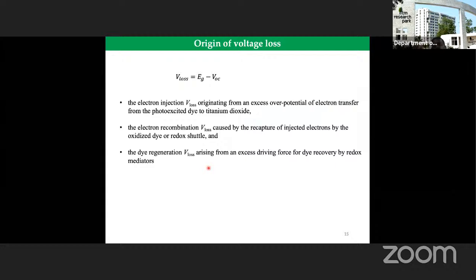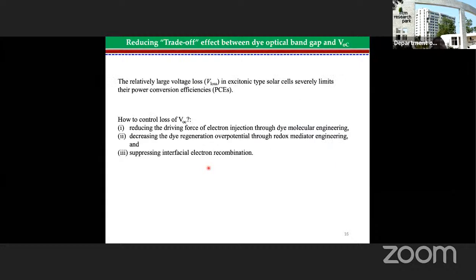So we need to control these 3, right? So how do you control this voltage loss? Reduce the driving force, that means a gap for electron injection, through dye molecular engineering. That's the only way. Decrease the dye regeneration over potential through redox mediator engineering, that means electrolyte has to be redone such that the HOMO is close to the redox energy of the electrolyte. And suppress the interfacial electron recombination, that is the back electron transfer. If we take care of these 3 physics, we will be able to significantly improve the VOC by avoiding the overpotentials.